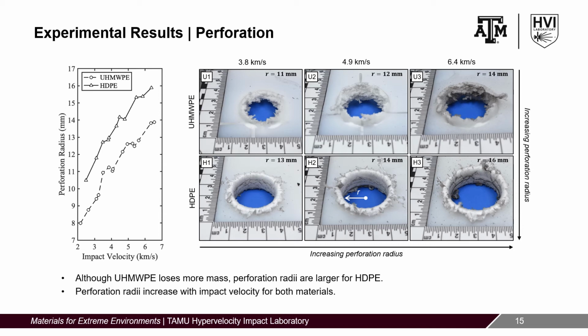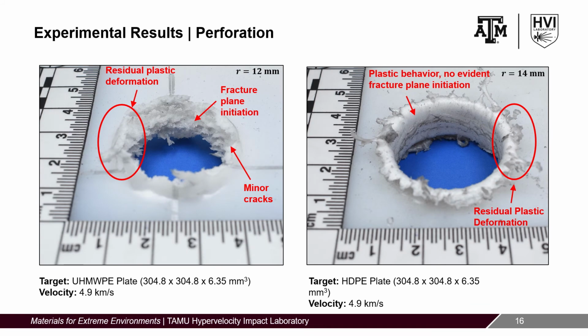The series of images on the right show the macroscopic characteristics of the damage regions for both materials. The images clearly show that, for both materials, the perforation radius increases with impacting velocity. Also, the perforation radii are larger in high-density polyethylene than ultra-high molecular weight polyethylene for the entire velocity regime tested. The images indicate that ultra-high molecular weight polyethylene failure is both brittle and plastic in nature. This results in multiple fracture planes initiating, while the plastic behavior and viscous effects prevent the development of dominant fractures.